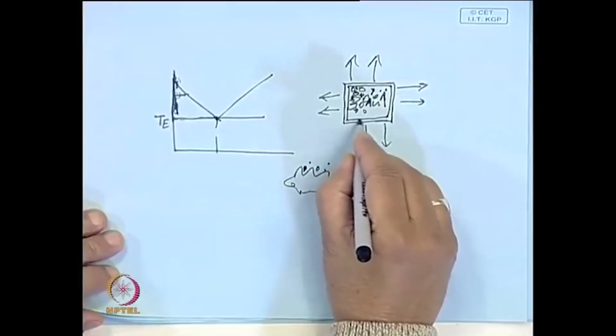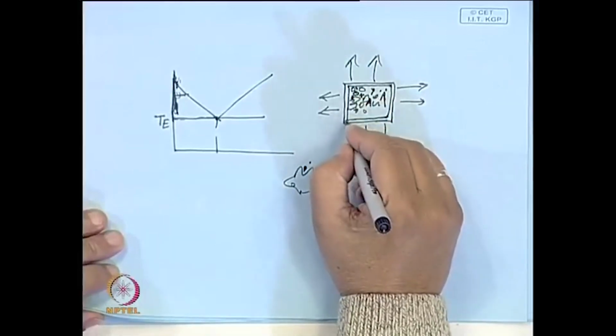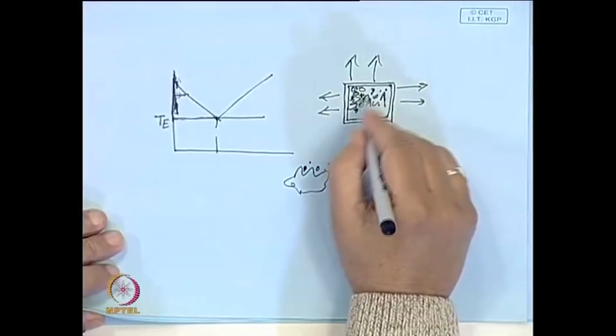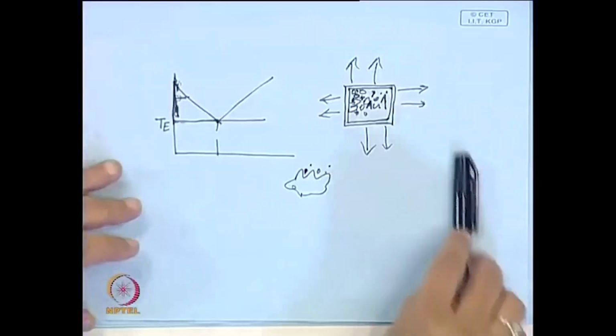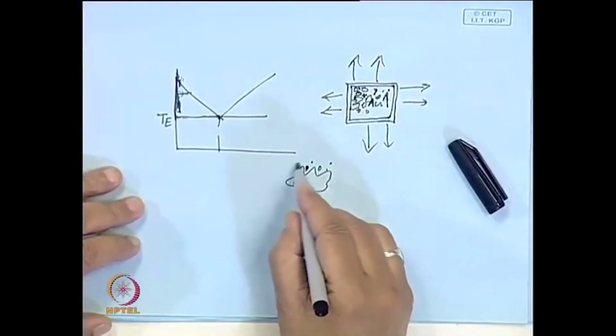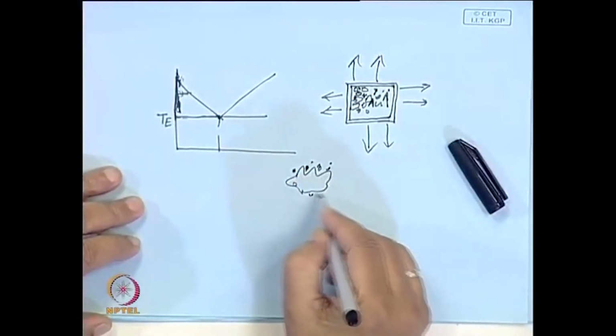So in reality, this is the defect-free, segregation-free region, and gas has segregated in the central portion, and this is what you get when you solidify alloys as well. When you solidify steel in a large mold, the steel will have dissolved gases, these gases will go to the center, and in the meantime if the top has solidified, the gas cannot come out. So in the central portion you will get gas porosity, and in fact these porosities will be present in the interdendritic channels.